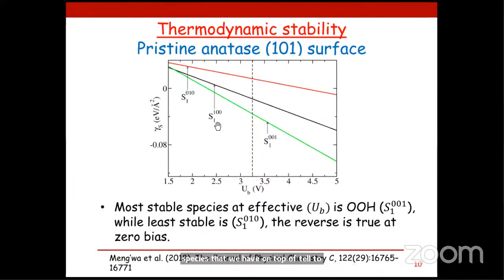So what we see is that the hydroperoxide species is more stable on TiO2, while the least stable is the hydroxyl species, that is the OH on TiO2, and the reverse is true when we extend this to zero bias. Remember that this bias is from 1.5 volts to 5 volts. So if you stretch this further to around zero bias, then we'll have the reverse.